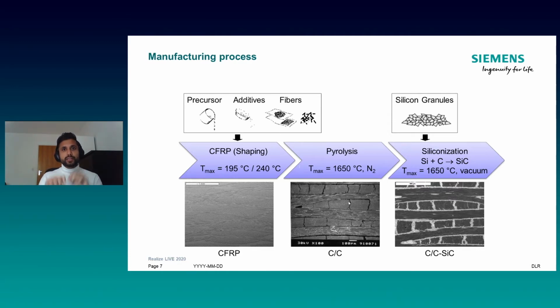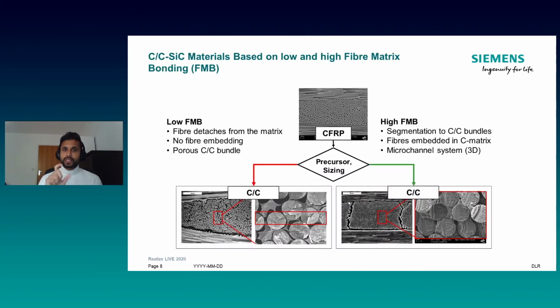And whenever the material is under thermomechanical load, we see a damage tolerant behavior, which is due to this block pullout, which we saw in the last slide. So what we need from our material is such a structure. And this block structure is dependent on the fiber matrix bonding. And the fiber matrix bonding, again, is dependent on the fiber and the resin I start with, right? So if I choose a fiber and a matrix which has low fiber matrix bonding,